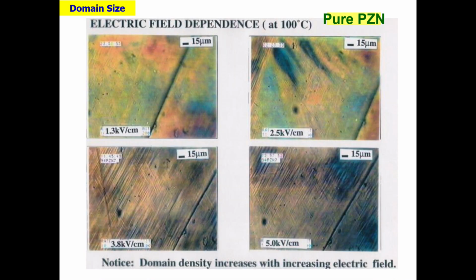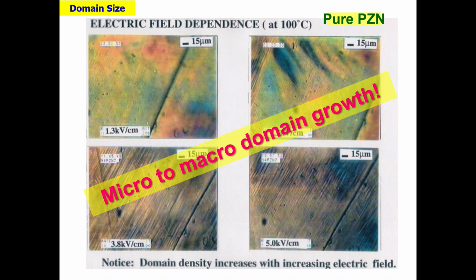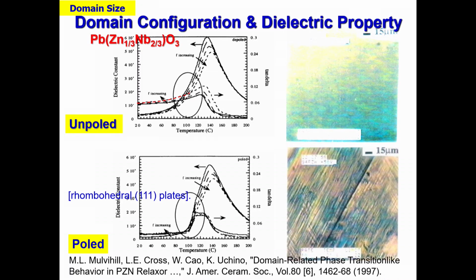So in the PZN, by applying an electric field, with increasing electric field, we can make visible macroscopic domains. And micro to macro domain growth happened with increasing electric field. So we found that very intriguing point.